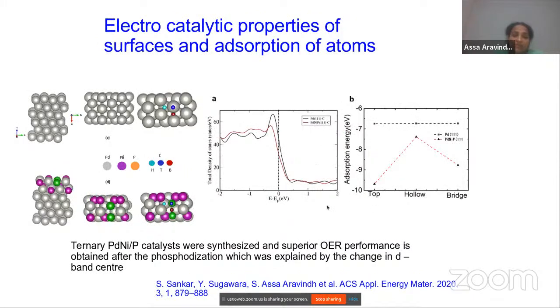And we could explain what is happening there, because we have to do a series of calculations to see where this carbon atom can go and adsorb, and then how the electronic structure is changing. And there is a theory by Norskov which shows that if the d band center is changing, it is favorable for catalytic reactions, and which was agreeing with the experimental results, and so we could successfully prove their results.